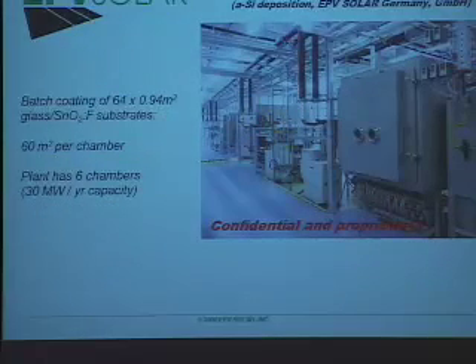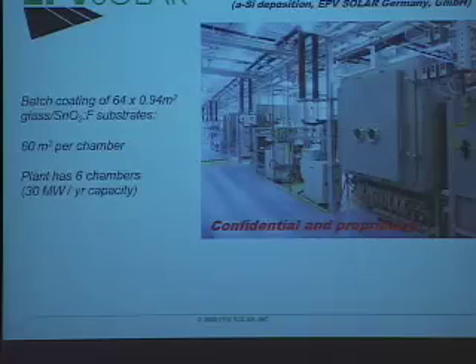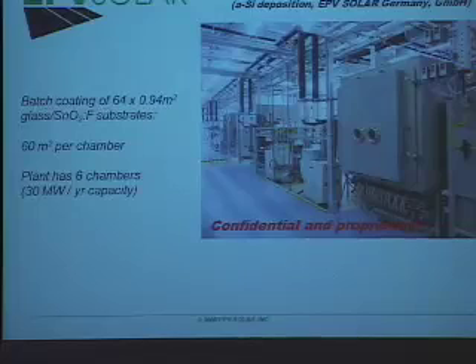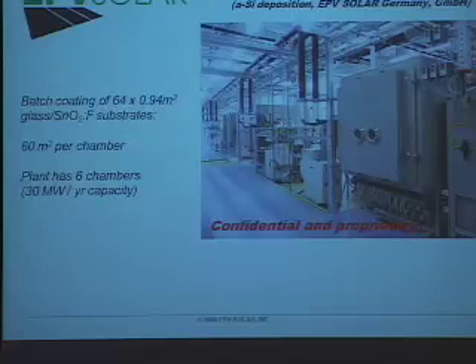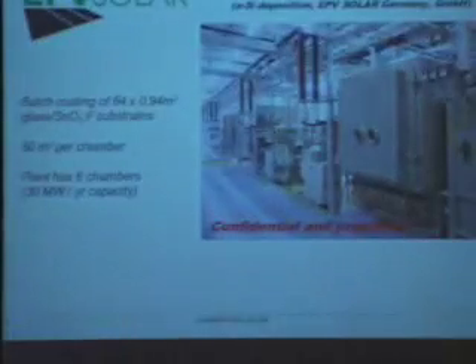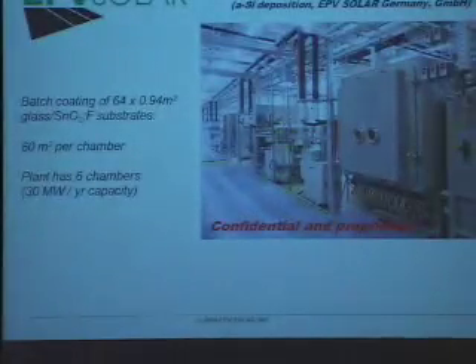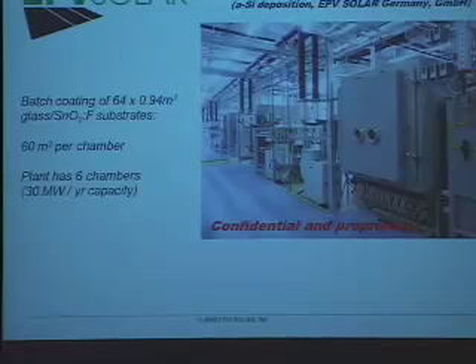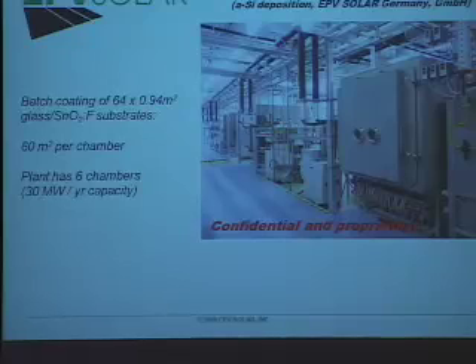This is a glimpse of our manufacturing. These are the plasma-enhanced chemical vapor deposition chambers that we use to grow the amorphous silicon, starting with silane as the input gas. We do batch coating. So in one of these chambers, we load 64 pieces of glass and we coat 60 square meters in a single run. The manufacturing plant in Germany has 6 chambers and with 30 megawatts per year capacity.